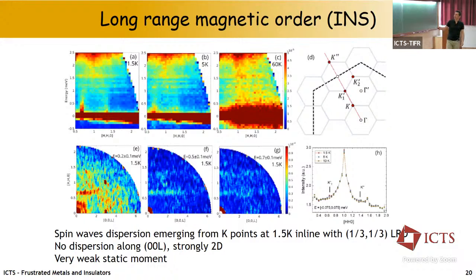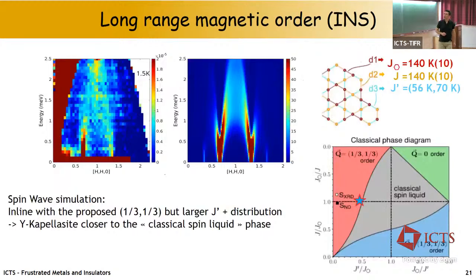Here is an attempt to integrate the signal in the elastic channel, and there may be small Bragg peaks at the K points, but it's really just at the limit of the noise. So in any case, the magnetic moment should be very small. And that's to answer your question, that's the simulation of the spin wave dispersion.